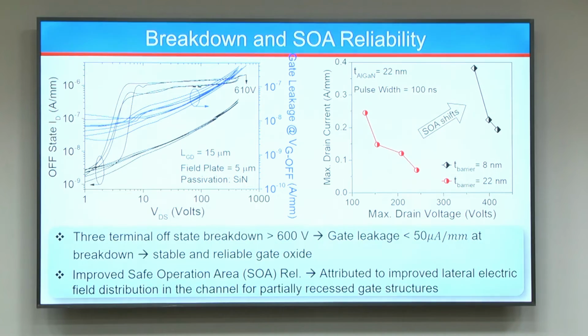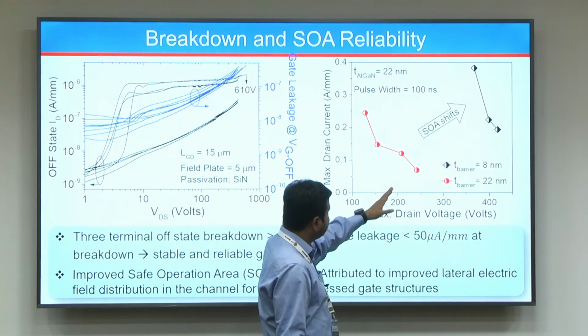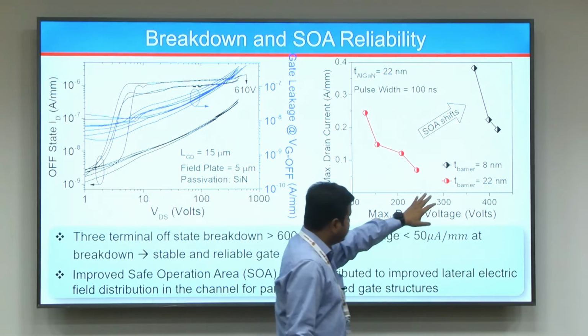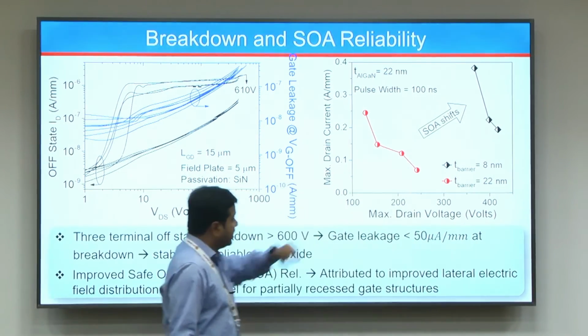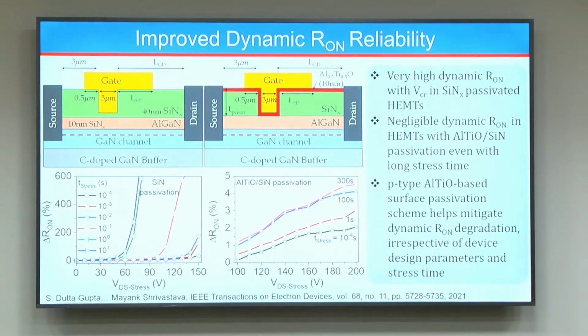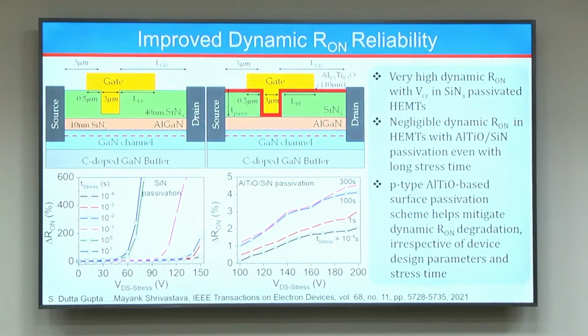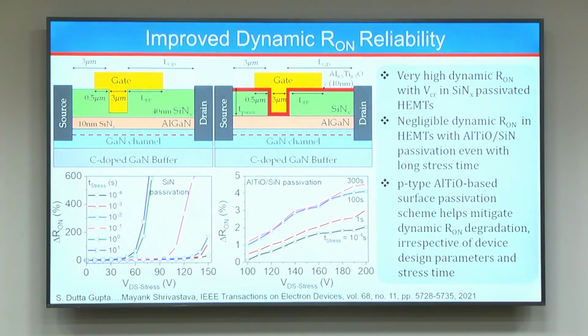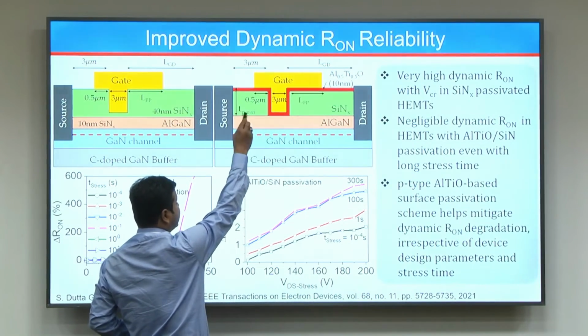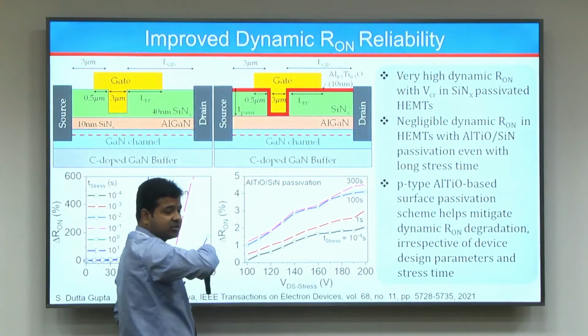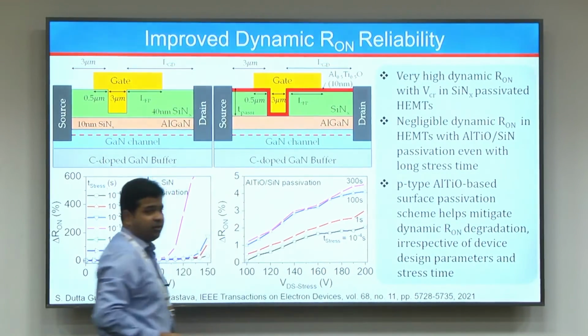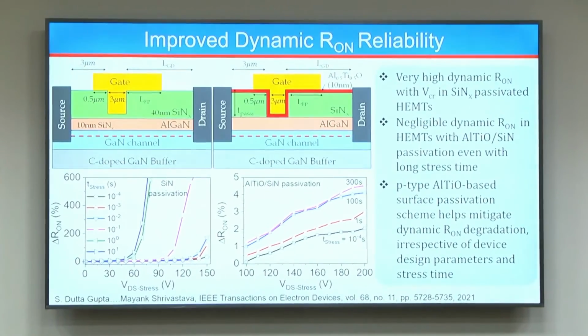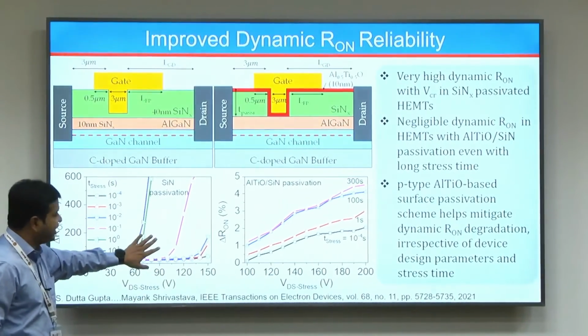Right, so there's some breakdown data, and we also did some SOA characteristics, and we found that because of the certain field configuration changes, the partial recess device with aluminum titanium oxide gives you better safe operating area compared to the previous one. And then we were parallelly studying the dynamic R-on, the physics of dynamic R-on, and what we found was that in our devices where the aluminum titanium oxide gate was used, the way the gate is done is you basically remove the in situ silicon nitride and then do this ALD aluminum titanium oxide. So the aluminum titanium oxide is also sitting in this region, and we found that these devices had much better dynamic R-on compared to the devices where only silicon nitride passivation was used.